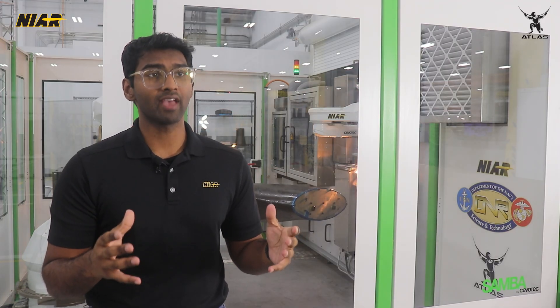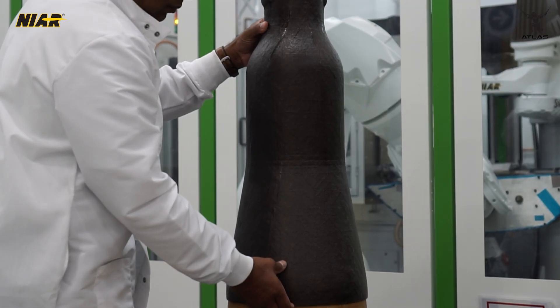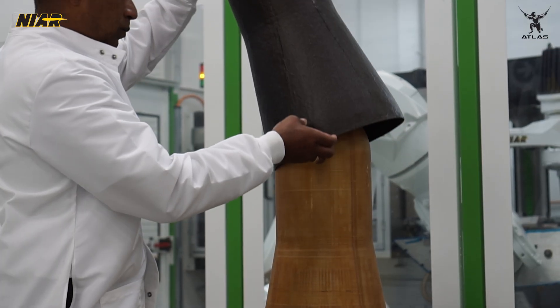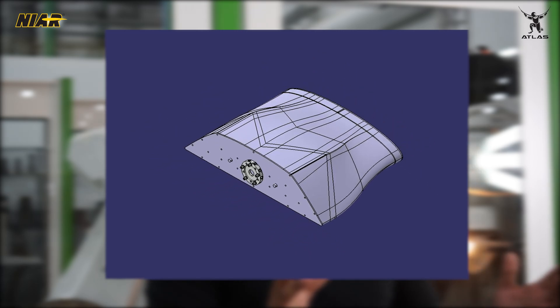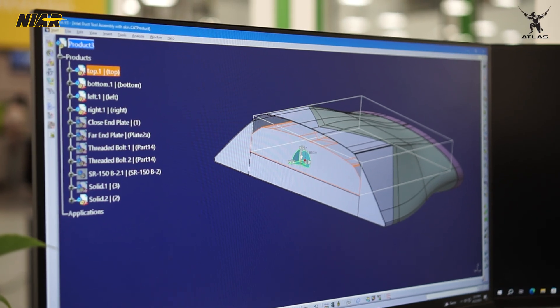Every part we make with AFP needs a tool to be laid up on. The 6-axis robot can hold tools up to 200 pounds. In most cases, we aim to design a tool where the composite parts can be removed like a glove after curing. But in the case of the inlet duct mouth, we faced tight edges and locking surfaces that forced us to redesign. We ended up with an assembly tool made up of four 3D printed sections held together with aluminum plates on either end. Once the cure is finished, we can remove the separate tool sections from within the composite part and pull them out one by one.